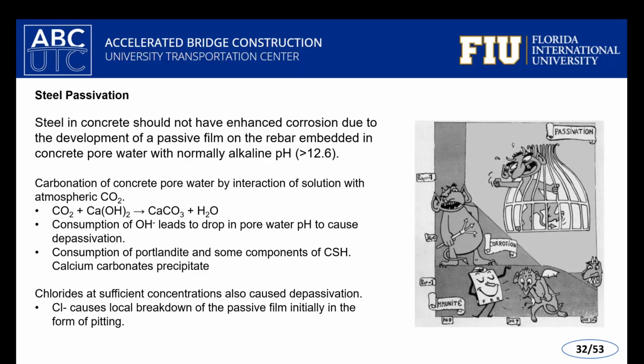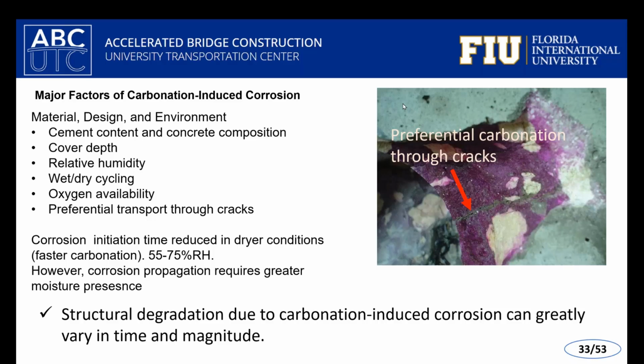And going back to Marcel Pourbaix's cartoon on the right-hand side, it gets to a point where the devil becomes more prominent as we shift from higher pHs to lower pHs as the hydroxyl ions are consumed. And so we'll talk about how UHPC can be useful to mitigate some of these effects. What are the major factors related to carbonation-induced corrosion? Well, evidently it's material related, and in part also design. The cement content you have, the concrete mix design, including UHPC, and the concrete composition are related to how permeable the concrete may be not only to moisture, but also to gases, including carbon dioxide and oxygen.